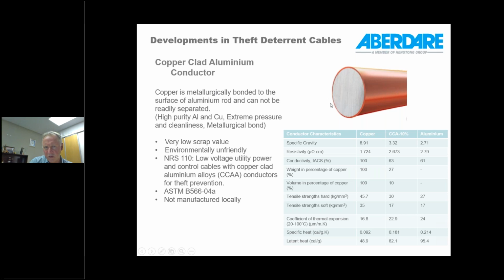These metals cannot be separated. They can only be separated if you make a poor quality product, so they're not intended to be a loose cladding onto the aluminium. It's supposed to have a solid bond. This conductor also has a very low scrap value due to the dissimilar metals. It is seen to be environmentally unfriendly in that there's very little one can do with this metal. You can recycle, and there are some alloys which can be made with aluminium and copper, but those are very specialized alloys, so it will probably end up in a scrap bin somewhere. So it is really problematic.